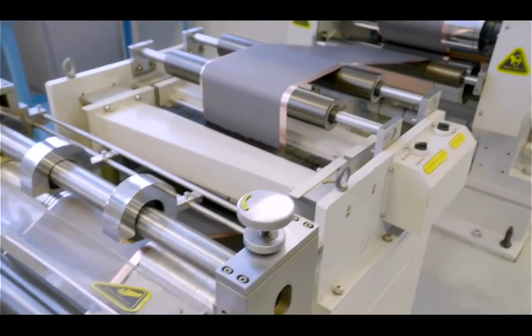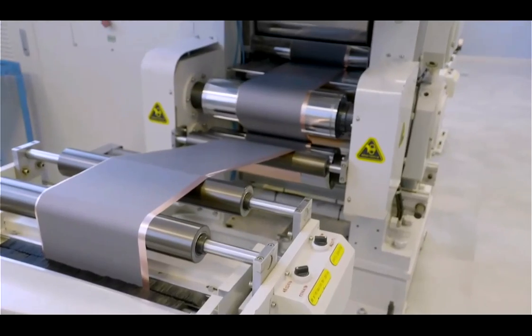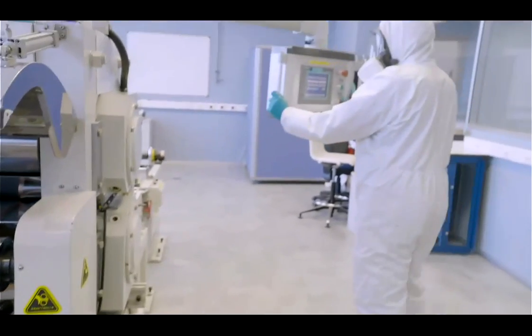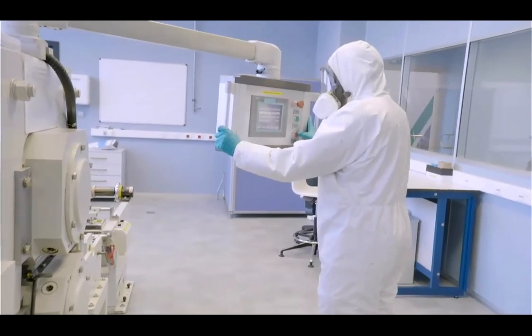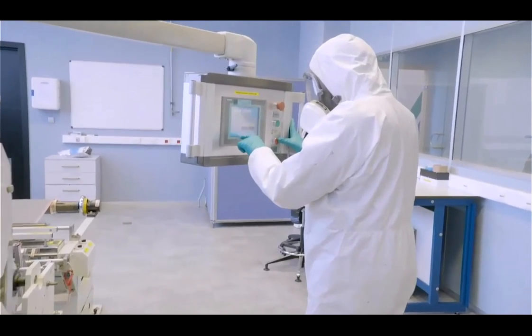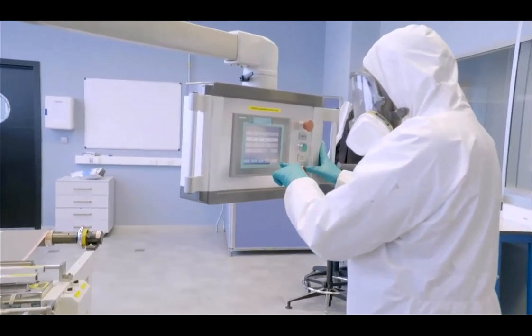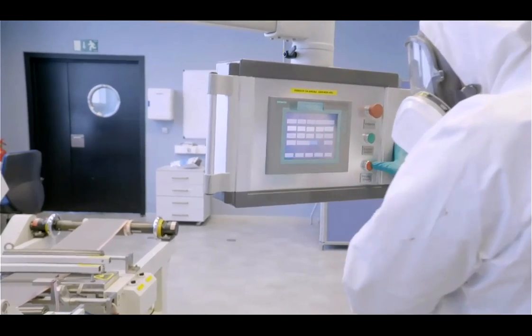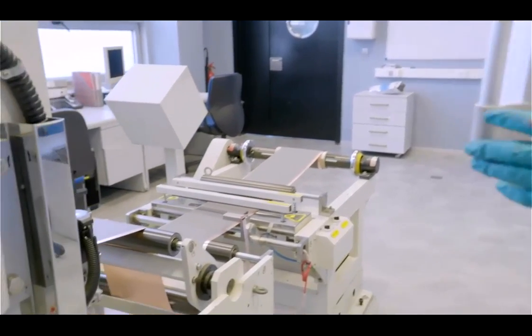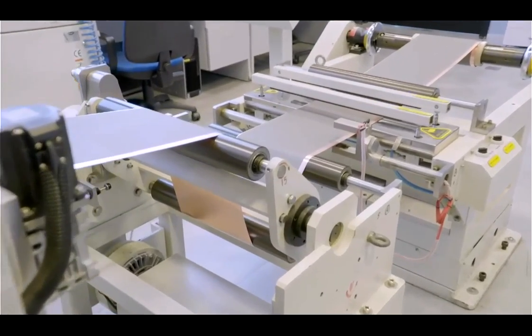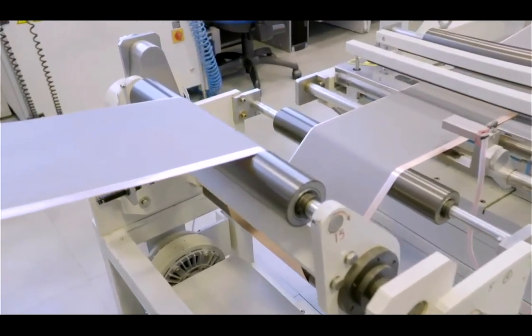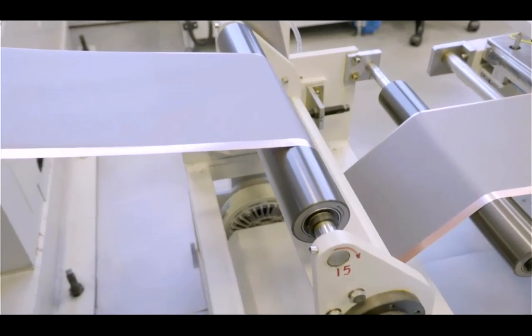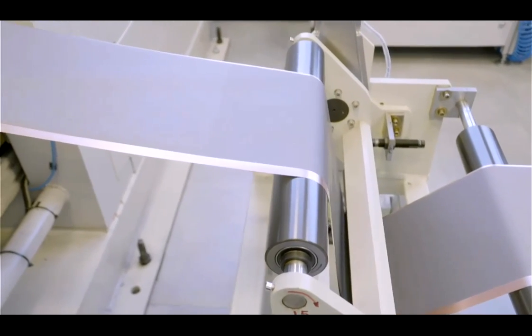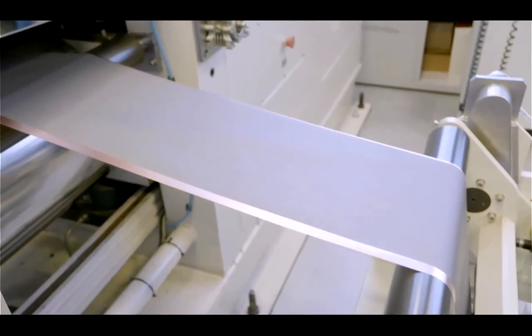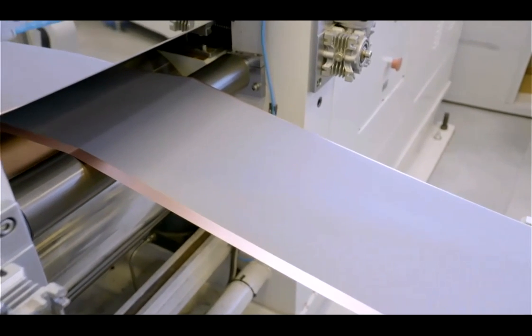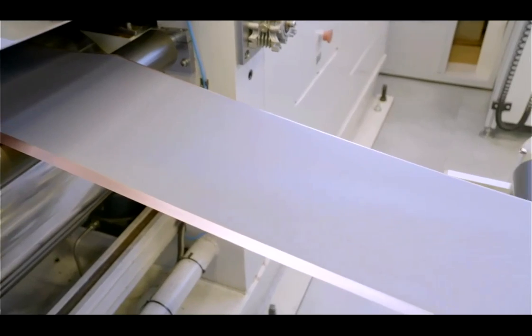The important part is what you see now in the image: these two big rolls. The parameters we can control in the rolls are the gap and the pressure. We have the possibility to warm up the rolls if it is necessary. It will depend on the densification that we are targeting, and on the chemistry. In general, during the calendering process, we will reduce the porosity from 50% that we have after drying to 20–40%. It will depend a little bit on the desired electrode configuration.